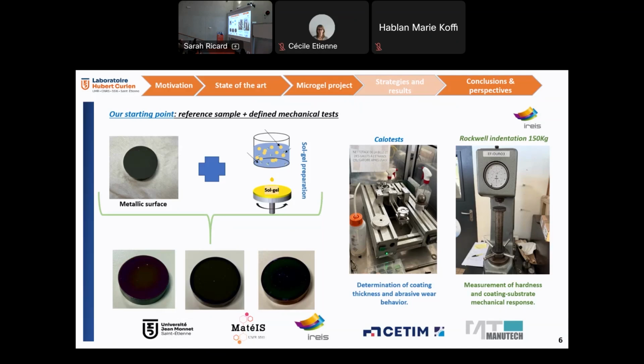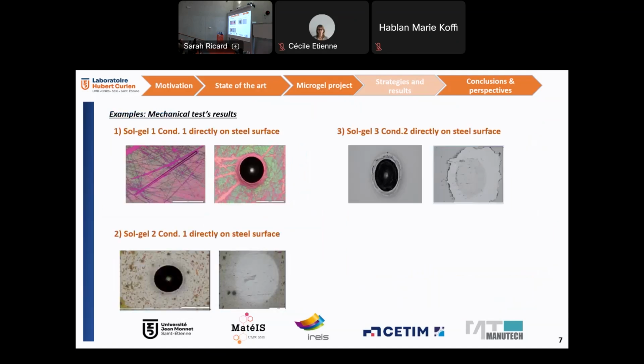So in the next slide, I would like to show you the preliminary results about this mechanical test. I cannot speak about the specific sol and the specific condition because we are working with companies and we want to patent it, but I would like to show you that when you are using sol 1, condition 1 directly on the steel surfaces without any strategy, you can see in this scratch test a lot of delamination in the sol coatings, and you can see the same in this Rockwell indentation, a lot of radial fissures close to this area, so it means that it is not a good result.